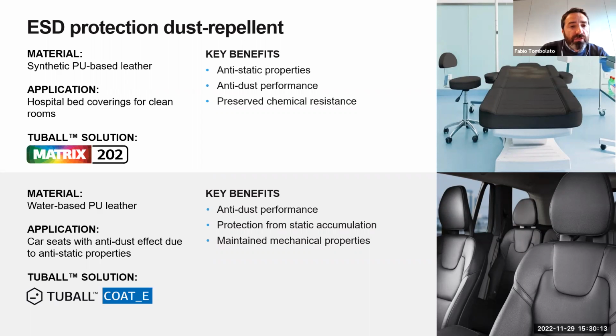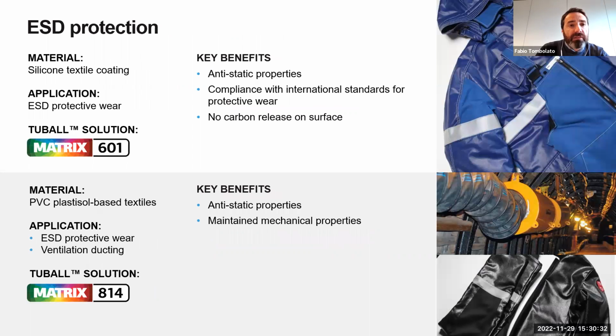Water-based polyurethane solution can also be obtained using our Tubal Coat E application for car seats. The properties that were achieved are anti-dust performances together with anti-static properties, maintaining the mechanical properties of the coating unchanged. ESD protective wear can be obtained combining the chemistry of silicone together with our Matrix 601. Anti-static properties that are compliant with international standards for protective wear can be achieved.